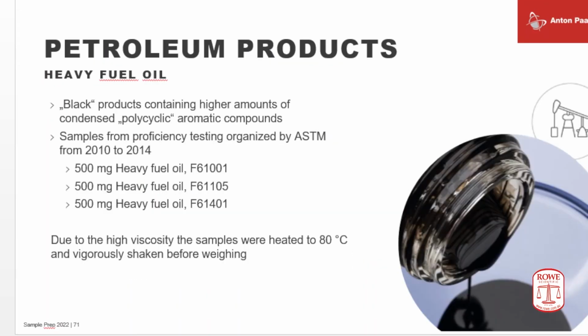Let's move to another group of samples, petroleum products. We have many users in the petroleum and petrochemical industry. The worst thing they have to deal with is this black, highly viscous, heavy oils, bunker oils, fuel oils. So these black products contain a lot of polycyclic aromatic compounds, which on one hand tend to react spontaneously, but there are some other compounds in there that need very high temperature to be broken down completely. So it's a quite critical combination: part of the sample reacts fast, part of it takes much longer time for complete oxidation.